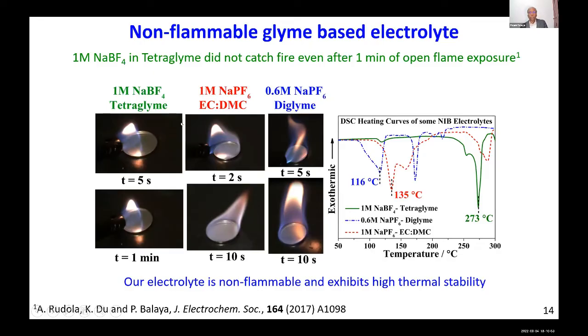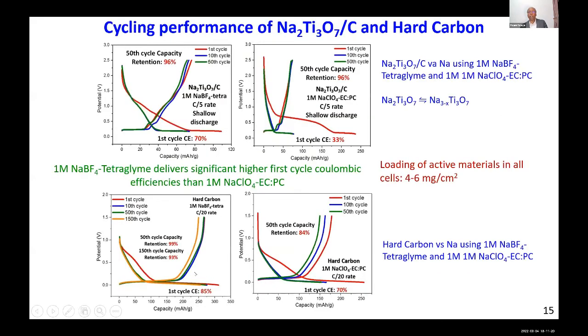Second point is, if you look at this green one, this is the DSC data. You can see here the thermal stability is pretty high, up to about 250 to 270 degrees centigrade. Whereas the red one, which is the carbonate-based electrolyte, undergoes a huge thermal event at about 135 degrees centigrade. This tells me that the glyme-based electrolyte we use is non-flammable, and it is highly thermally stable compared to the rest of the electrolytes. This particular electrolyte, this so-called tetraglyme, has been used with different cathode materials.